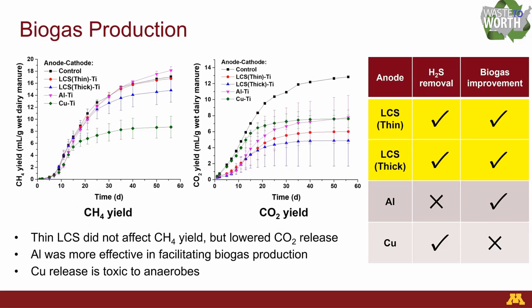So we examined the biogas production simultaneously. We can see the low carbon steel anodes did not affect the methane production significantly, but they all reduced the carbon dioxide release. Aluminum was actually effective in facilitating the biogas production, but copper seems to be toxic to the microbes, which reduced the methane production significantly. So when we combine the hydrogen sulfide removal and the biogas production, we can say low carbon steel is a viable sacrificial anode material to achieve the two effects simultaneously.